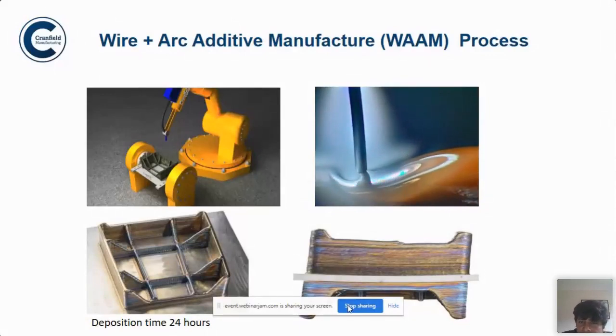Whereas in wire plus arc additive manufacture, you see on the right hand side, the ongoing video is basically you feeding a titanium wire into a welding arc. On the left hand side, it is an animated image. However, on the bottom, you can see the real component. So this is a landing gear box made of titanium, and as you can imagine, creating this type of component in a laser plus powder system will be very, very difficult, because the size of the component is in meter scale rather than millimeter scale, and the dimensional resolution that you need is not as high as that. So you can machine this and make your component.